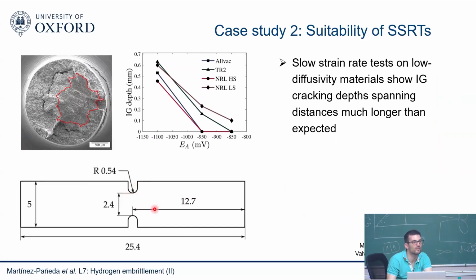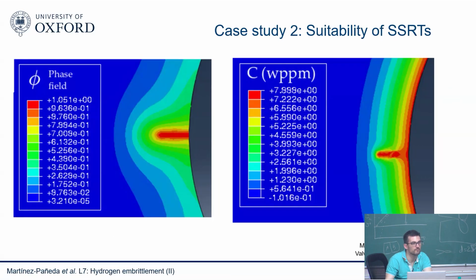No worries. So then the question that I have is, if you look at the range of concentration in the interior, the bulk of the specimen, it's 0, is it? Yeah, the concentration is roughly 0. But shouldn't you expect that there would be some lattice concentration still there if I have achieved steady state diffusion for the entire concentration? But we never achieve steady state diffusion because these are nickel alloys, so the diffusivity is super low. Okay. So you actually only get very little hydrogen uptake.